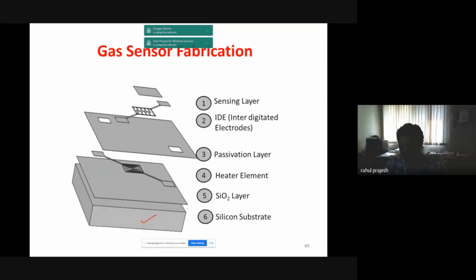So you have a substrate, a silicon substrate, then you have a silicon dioxide layer, so that the metal micro heater, the third layer, is isolated from the silicon substrate. Then there is a passivation layer. This passivation layer is made of silicon nitride most of the time, because silicon nitride is electrically insulating and thermally offers good conductivity, so that your micro heater is able to give complete heat to the sensing film. So this film should be electrically non-conducting, but thermally it should be conducting. Then you have electrodes, and on top of that you have the sensing film.